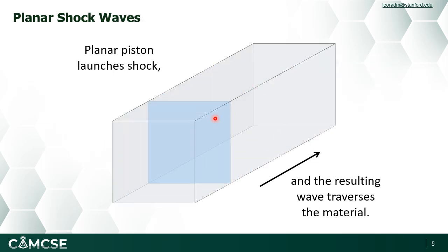So when we launch a shock wave, typically we try to launch a shock wave in a way that allows us to consider the shock not as a complex shape, but instead as a nearly planar mechanical wave that propagates along a linear direction of propagation we can define along one axis. So largely, when we generate shock waves, we try to generate them in such a large region that the regions that we probe are nearly planar, or have a nearly planar shock response across the region of interest we're sampling.